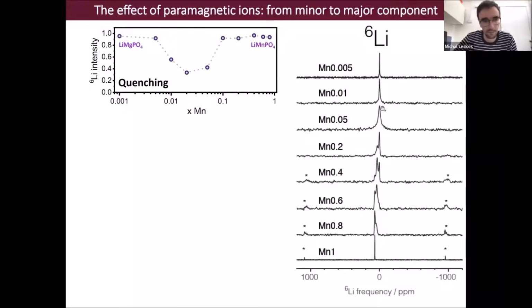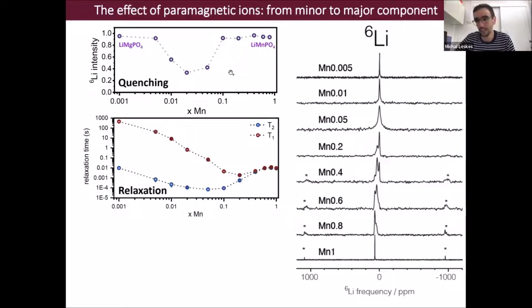So here is for lithium-6, which is the cleanest nucleus that I showed you before. We quantified the signal intensity as a function of the moles of sample that we have in the rotor, and we see that the signal intensity drops with increasing concentration, same as I was showing before. However, if we keep growing the concentration of paramagnetic centers, at some point this trend inverts and we start seeing more and more lithium nuclei again, until at this high concentration, we are able to virtually see all nuclei again.